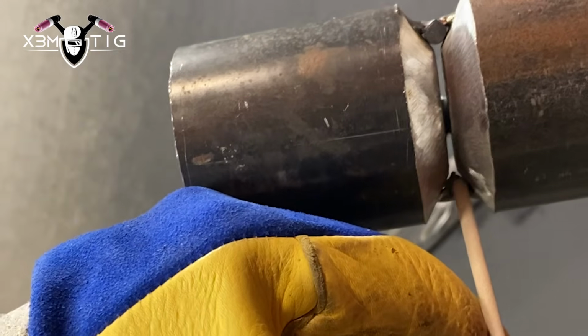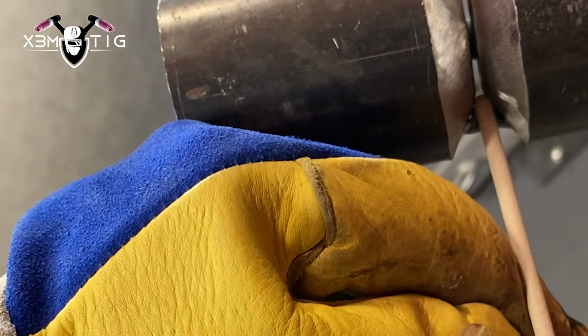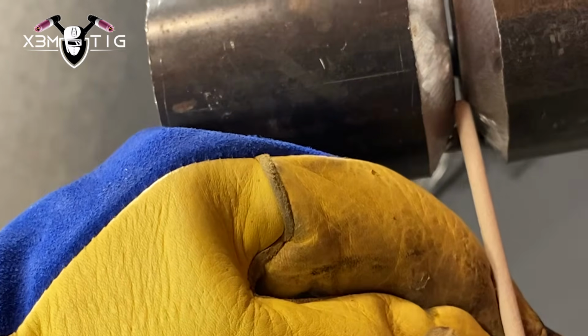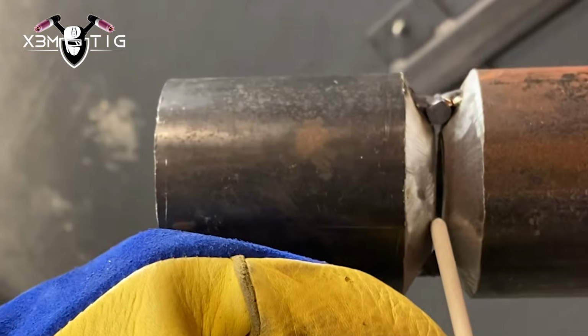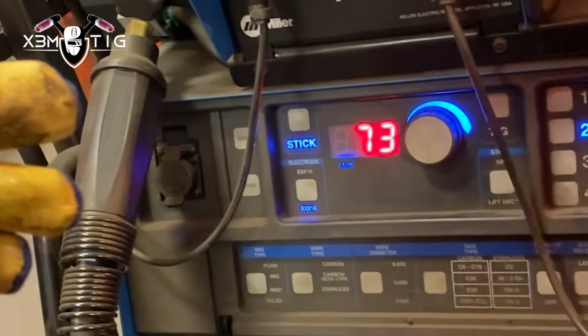So with the keyhole technique, the length of the whipping stroke should be approximately 1.5 times the diameter or less. When you start with 6010, you want to pause a little bit at the bottom. The rod should pause at the bottom of the keyhole long enough to deposit metal, and raise up enough to keep keyhole size consistent and allow the root time to cool. There's an old school rule of thumb: if you hear that crispy sound when you're burning your root, then you know everything goes well. If you don't hear that crispy sound, then you should stop, and something's probably not right.